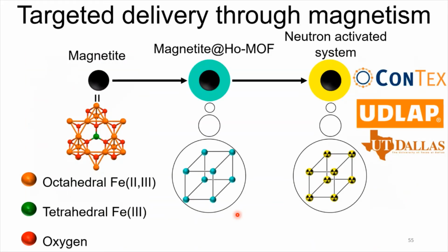The first application is delivery through magnetic particles. This is very similar to the garnet, but the problem with the garnet is that it is not as strongly magnetic as magnetite, for example. So when you want to target something in deeper tissue, it's harder to get there. My lab mate, Jason, was working on trying to get magnetite and some silica cover to get the holmium transported. But we thought, what if we coat this magnetite with the MOF system? Can we end up with a delivery system that is magnetic and has the holmium and has the porosity?